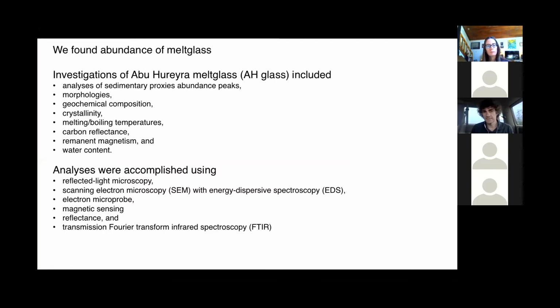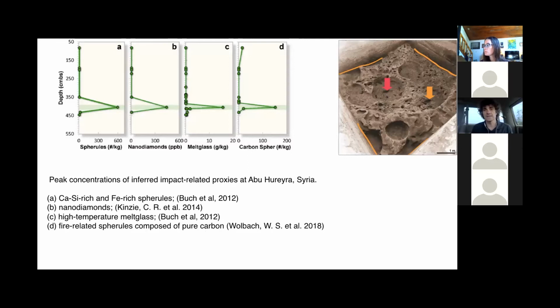We did analysis of sedimentary proxies in this layer for abundance peak, morphologies, geochemical composition, crystallinity, boiling temperature estimate, carbon reflectance, remnant magnetism and water content. For that we used SEM analysis, reflected light microscopy, electron microprobe, magnetic sensing, reflectance, and FTIR. To give you an idea, there's a depth profile, and at very specific depths near 4 meters, you can see an abundance of microspherules, or spherules, which are millimeter size, up to about 600 per kilogram of layer sediment. There are nanodiamonds that go almost up to 450, 500 parts per billion. There's melt glass at about 16 grams per kilogram, and carbon spherules are also abundant, about 160 per kilogram.